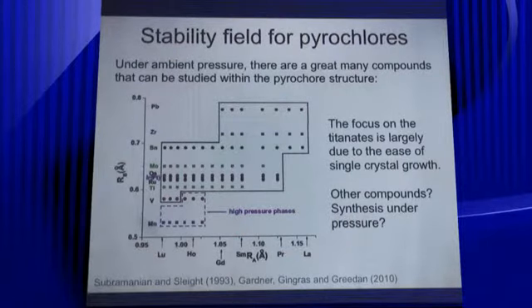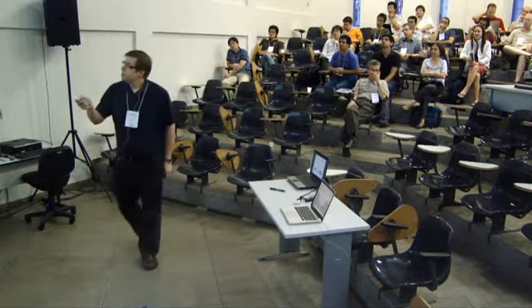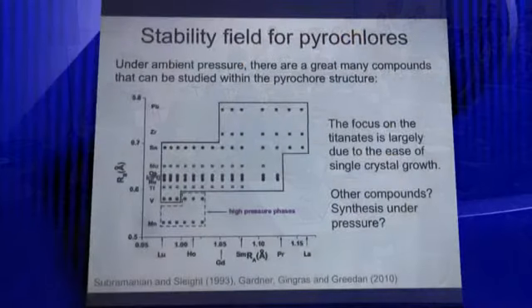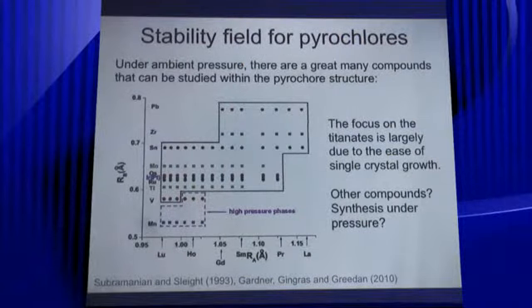Actually, a stannate would be a wonderful system to systematically look through many pyrochlores, but there are problems with the stannates. There are chemistry problems with stannates, right? So you have stoichiometry problems with tin oxide at high temperatures, and you have to be really careful when you're trying to compare different or the same stannate compounds with each other. But I'm going to talk about where we want to look for new spin ices beyond the titanates. Notice there are these high pressure phases that I've emphasized here. We're going to talk about new high pressure phases, in particular the germanates, near the end of this talk.